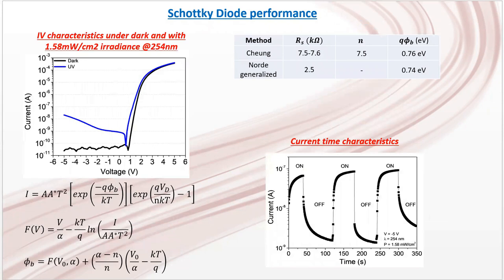Shown here is the performance of our Schottky diodes. You can see very clear rectification behavior in this graph on the left-hand side with turn-on voltage around 0.7 volts. The performance in this case is not particularly good because we chose to use PVD deposited gallium oxide rather than epitaxial material. Nevertheless, we get measured good Schottky device performance, and a number of different approaches can be used to actually calculate characteristics such as the diode ideality factor and the Schottky barrier height, and these are in quite good agreement.